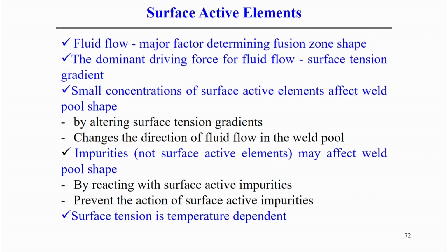But there is one question: the composition of this molten pool sometimes plays an important role in the nature of the material flow within this small weld pool. So, one such interesting element of analysis in the material flow is called surface active elements. In a simplified way, surface active elements actually influence the surface tension force. The surface tension force acts between the liquid molten pool and the shielding gas.